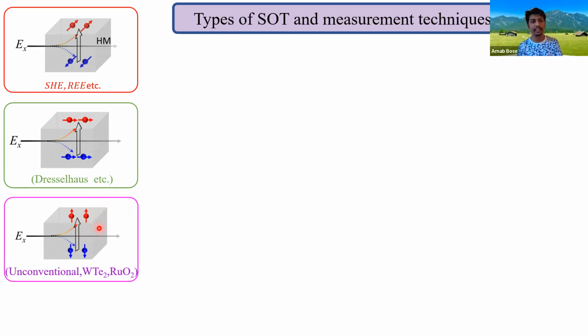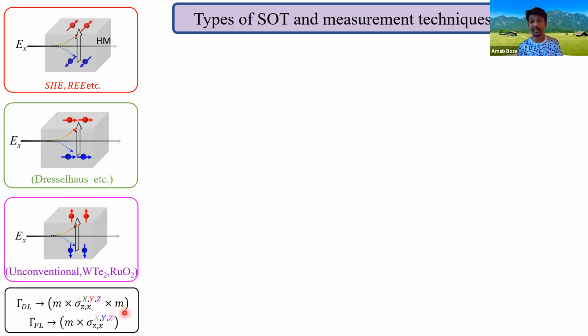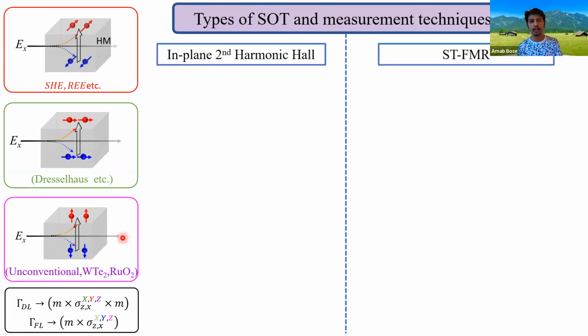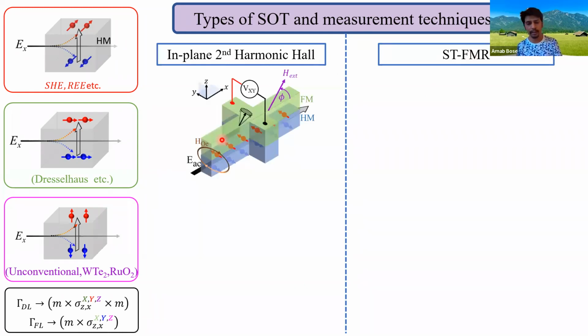Now, if we have an adjacent magnet that can absorb the spin current, it can experience six different types of torques, three different types of damping-like torques and three different types of field-like torques. Now, by looking at the different types of torques, we can exactly know what type of spin current is generated. So we need to know experimentally how to quantify and identify all these types of torques. So there are two standard methods. One is second harmonic Hall and another is STFMR. So let me first start with the second harmonic Hall.